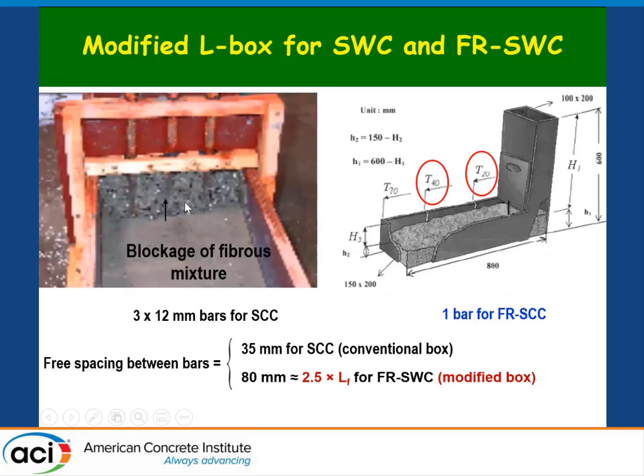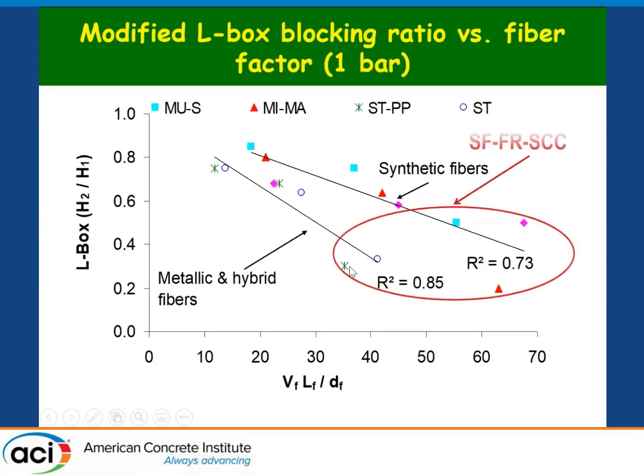And in terms of the L box, you can still use the L box, but instead of using 2 or 3 rebars, when you are using super workable concrete or fiber reinforced super workable, we recommend using only 1 rebar and doing the test. If it does not really spread all the way, to give you the blocking ratio, you can insert a pencil vibrator and document how long the pencil vibrator was in that vertical compartment. So you have the L box, again, metallic fibers, synthetic fibers, and these are the super workable consistencies.